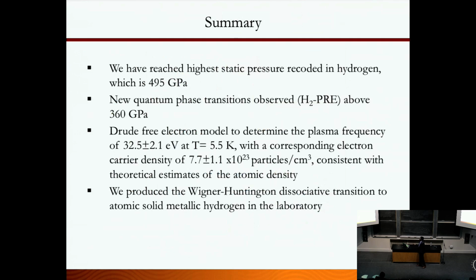So in summary, we have reached a record pressure of 495 GPa, and we observe a new quantum phase transition. The Drude electron model gives you the parameters, plasma frequency and electron density, and we produce the Wigner-Huntington dissociative transition to atomic solid hydrogen.